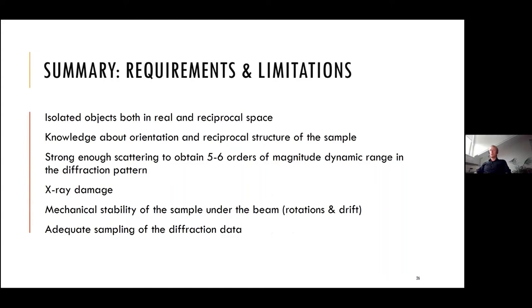You better know the orientation of your crystal so that you know where the reflection you're looking for is. That can be supported by some Laue measurements or electron microscopy measurements, so you actually know how your sample is aligned with respect to the substrate. You need a material which scatters enough photons, so like 5-6 orders of magnitude of dynamic range would be perfect data to reconstruct. The lower it goes, the more difficult it is.